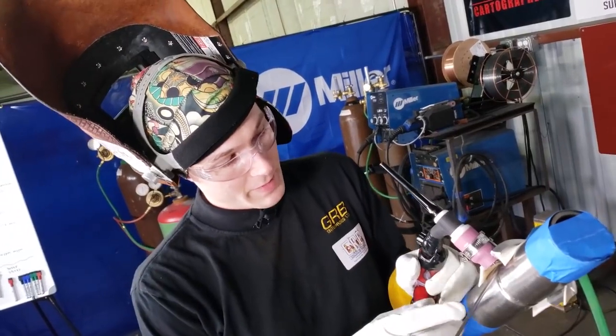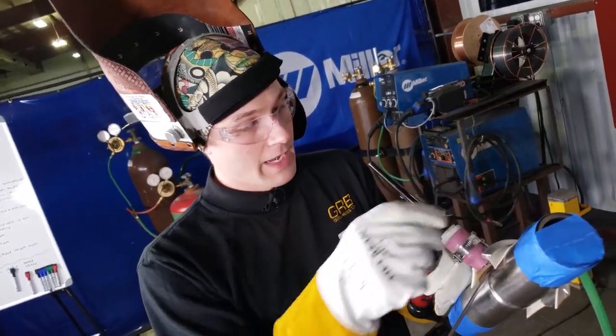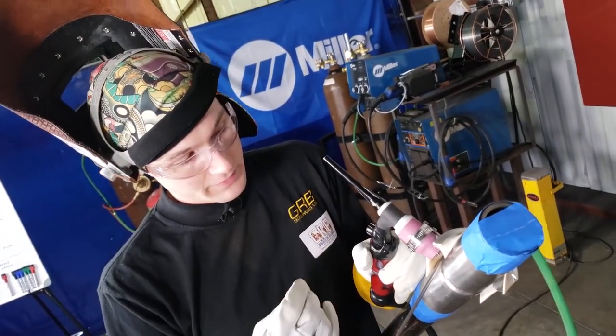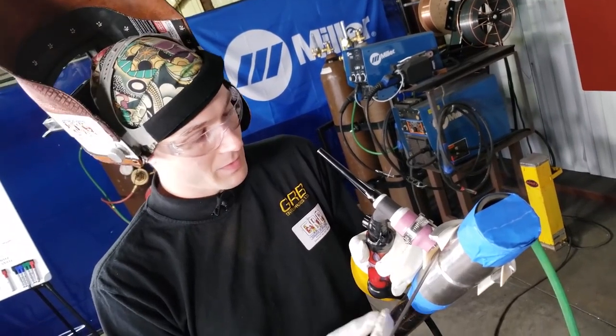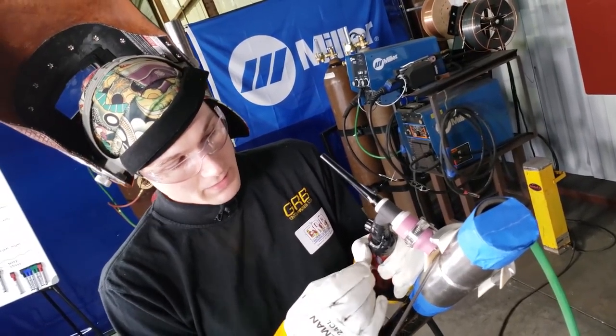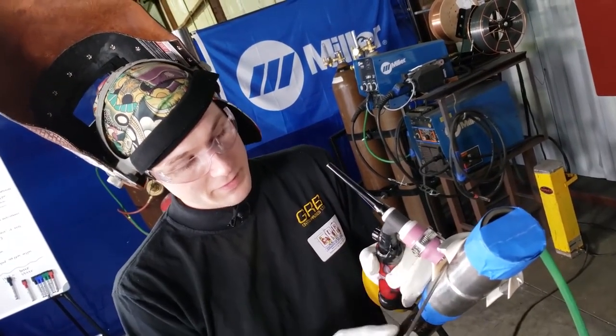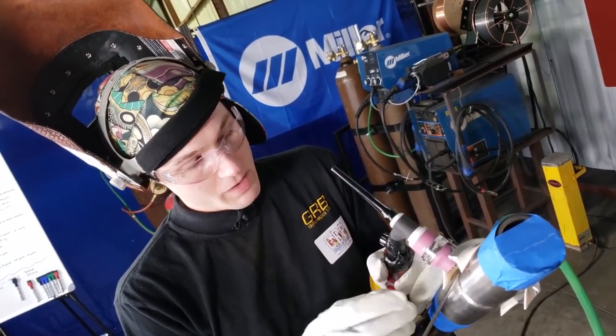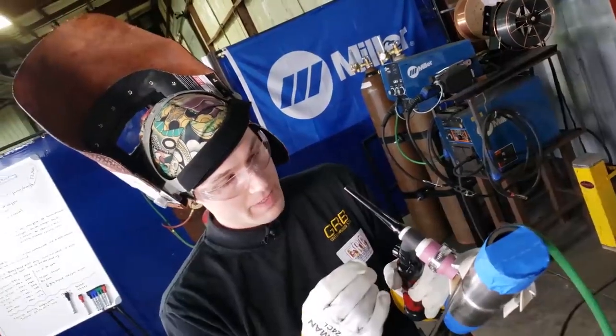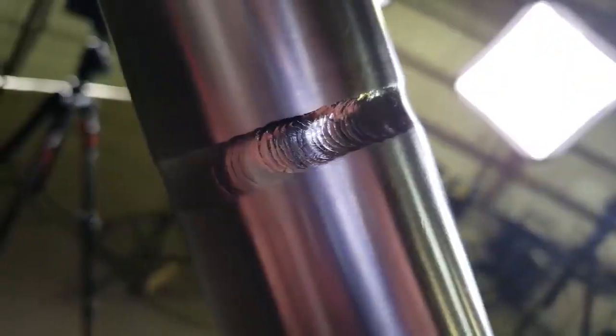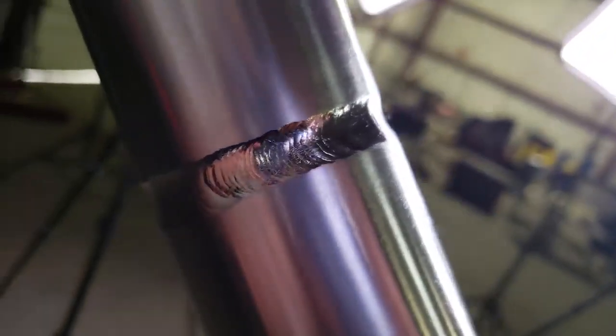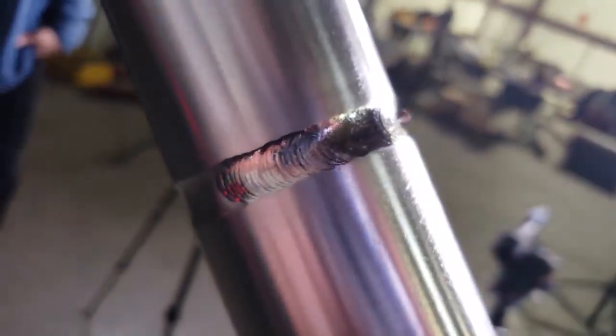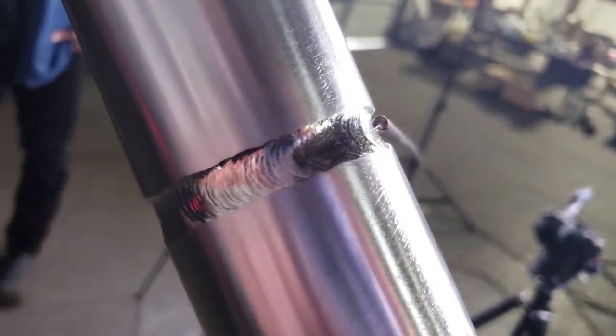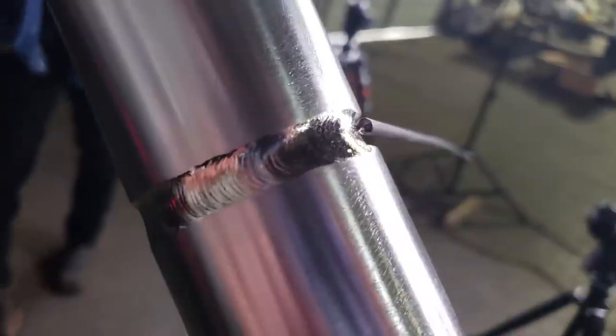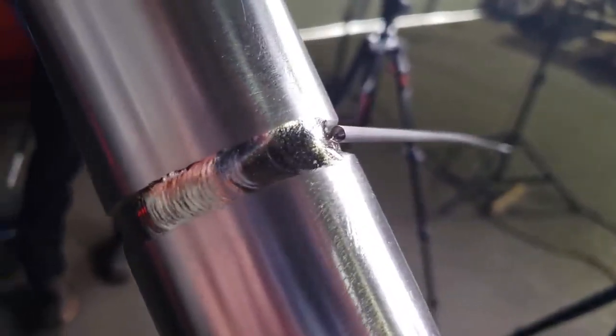Also, I should mention that depending on the temperature, and how much energy in joules is expelled into the material, and depending on what technique I've used with this deposition of the metal, how hot the metal is and the temperature that the metal will be at when it interacts with the atmosphere determines how long I hold the trailing shield and/or individual ceramic cup on the deposited metal to protect it away from the atmosphere.